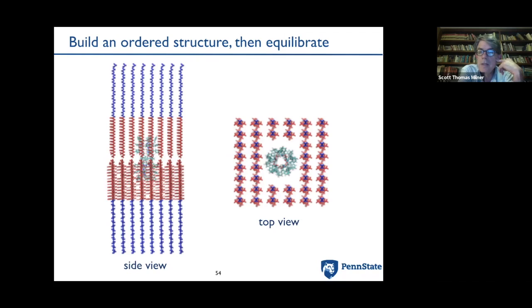And so the technique that we've used to build this thing is roughly like the orchard technique that you saw. You build an orchard of these surfactants, in effect, with a space in the middle for the pore molecule, like a fountain in the middle of the Tuileries or something, and then you have an upside down version of it below, in order to make the other side of the bilayer. And then by degrees you equilibrate this thing, first energy minimizing it, which tends to make the molecules clump together, with the pore frozen so as not to mess up the shape of its petals.